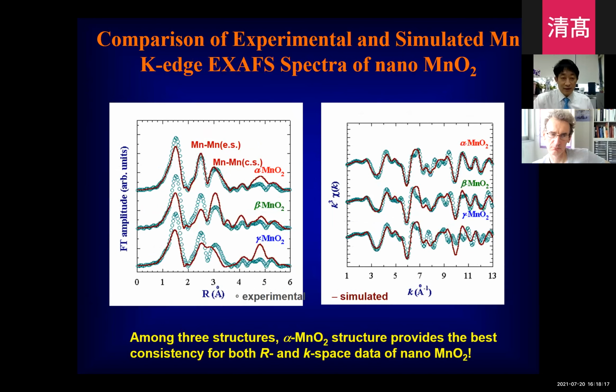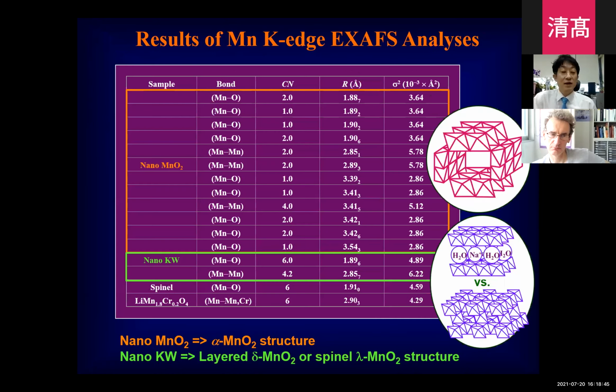I already explained to you that there are three types of manganese oxide lattice containing the edge sharing and the corner sharing of the MnO6. But each structure shows a different ratio of the edge sharing and corner sharing. The red line is just a simulation, it's not the fitted data, but without fitting, this shows very good matching for the ratio between edge sharing and corner sharing. Based on that we can successfully fit the experimental XAS spectrum of nano MnO2 as the alpha MnO2 structure.